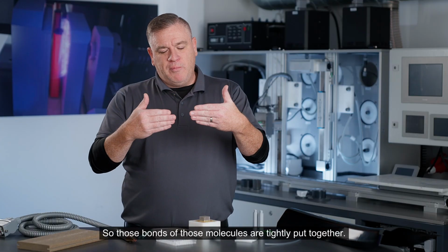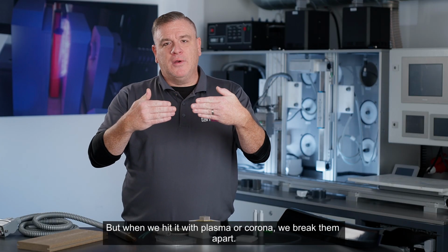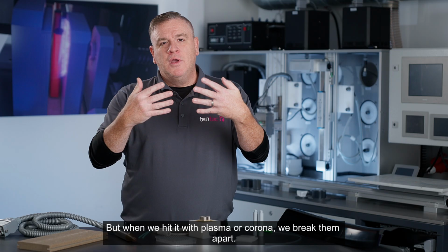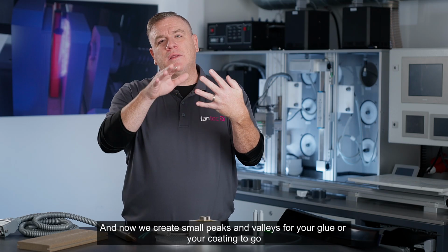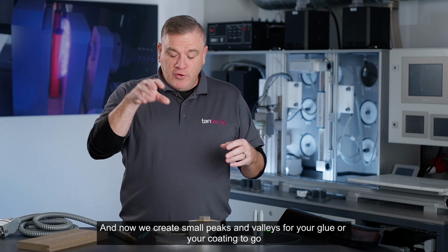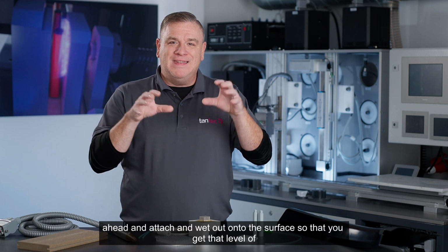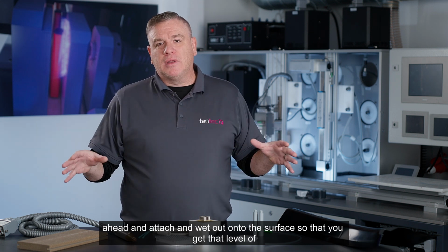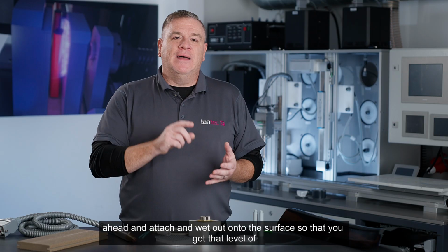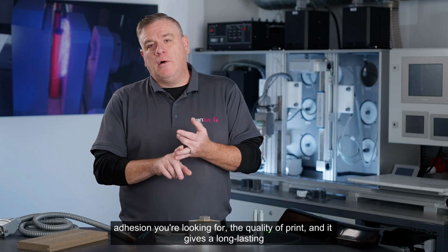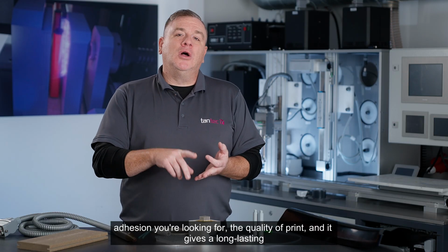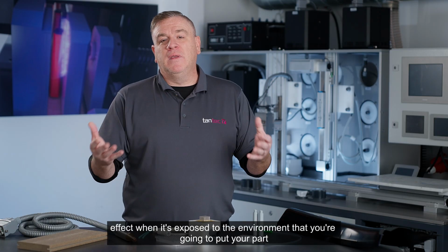So those bonds of those molecules are tightly put together, but when we hit it with plasma or corona, we break them apart, and now we create small peaks and valleys for your glue or your coating to go ahead and attach and wet out onto the surface so that you get that level of adhesion you're looking for, the quality of print, and it gives a long-lasting effect when it's exposed to the environment that you're going to put your part into.